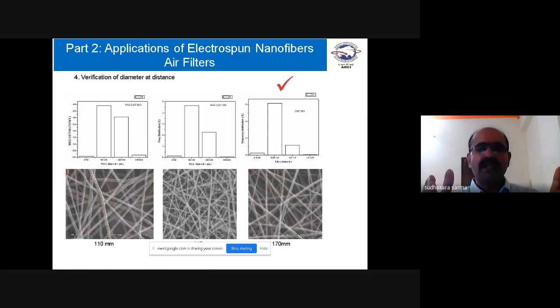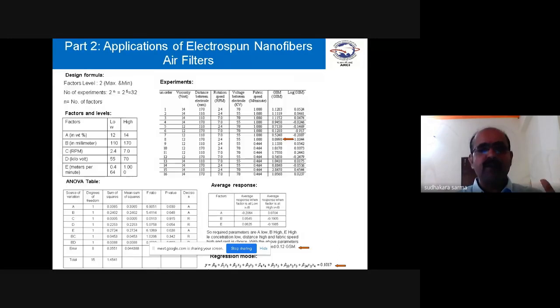And at 170 mm distance between the electrodes, we have got the fiber diameter of 50 to 100 nanometers. More fibers are 50 to 100 nanometers. So with that, we have optimized the process parameters. We have checked the fiber diameters with the Taguchi experiments.